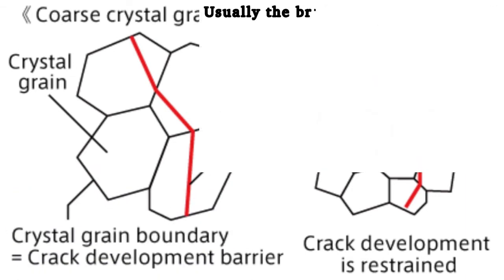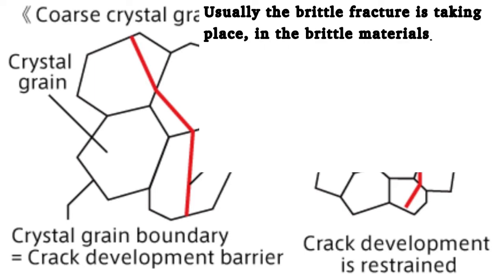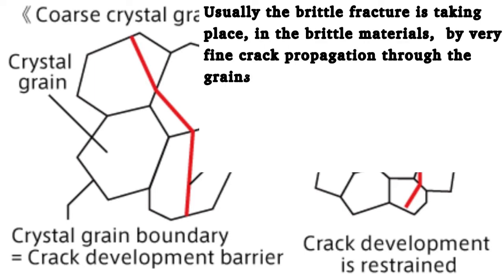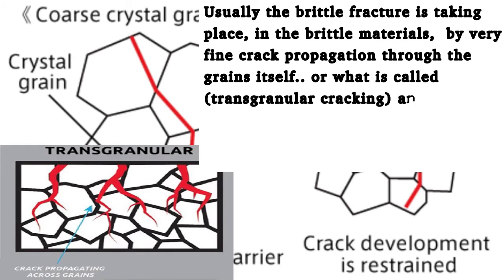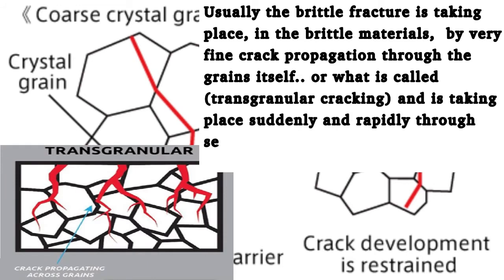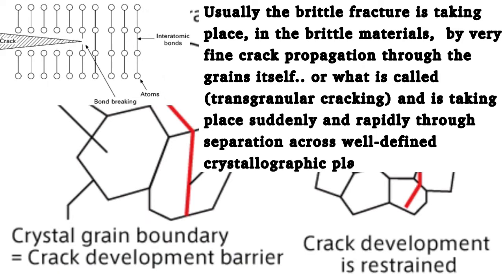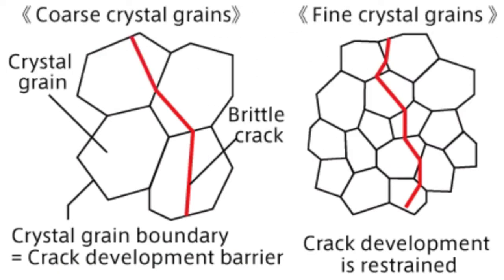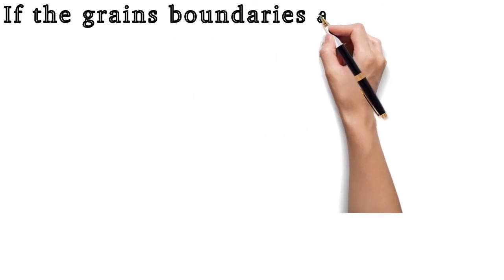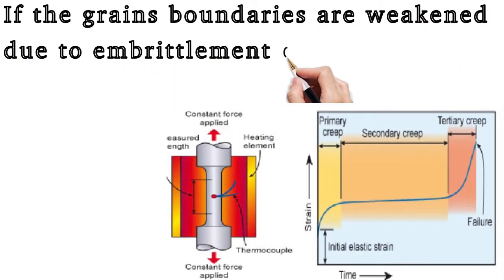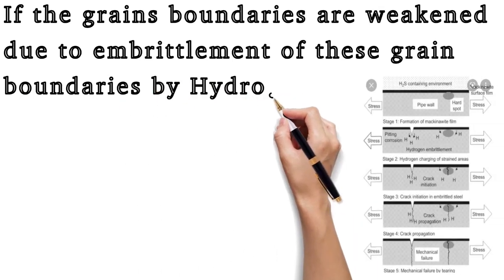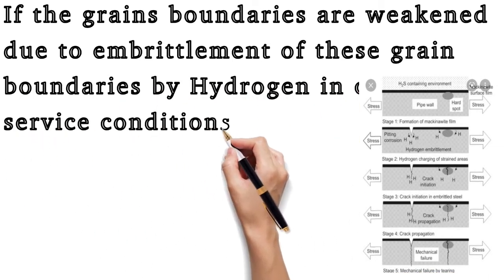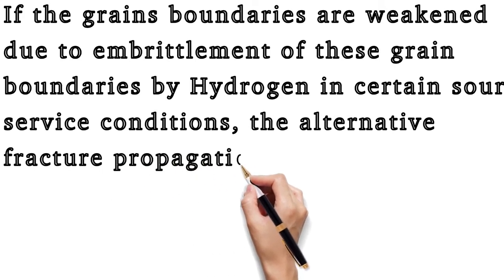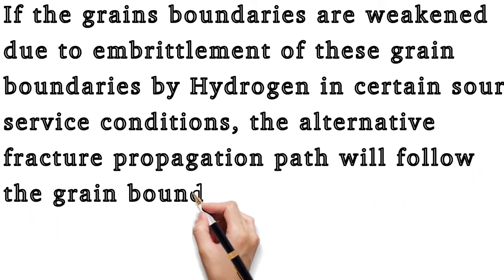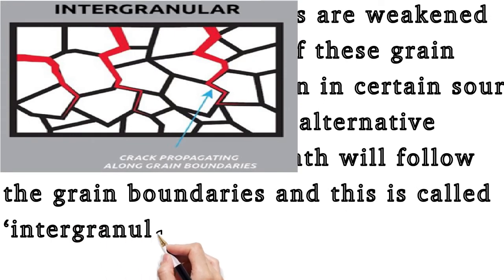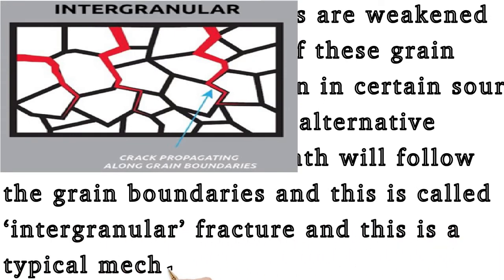Usually brittle fracture takes place in brittle materials by fine crack propagation through the grains themselves, or what is called transgranular cracking, and takes place suddenly and rapidly through separation across well-defined crystallographic planes. However, if the grain boundaries are weakened, like in the case of working above a certain high temperature called creep temperature, or in case of embrittlement of these grain boundaries by hydrogen in certain sour service conditions, the alternative fracture propagation path will follow the grain boundaries. This is called intergranular fracture, and it is a typical mechanism of sulfide stress cracking failure.